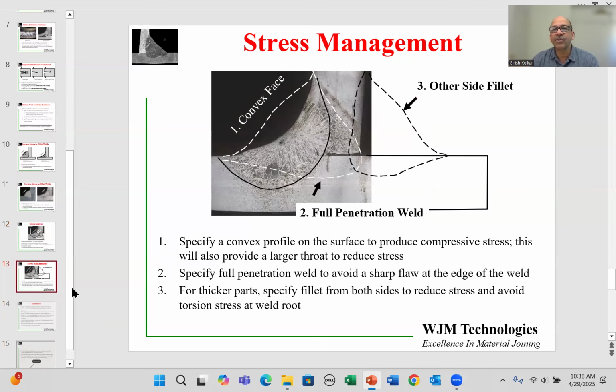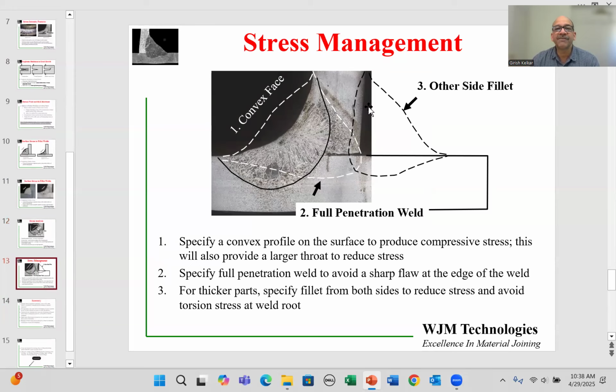So what can we do to manage the stress? The first thing you can do as a design engineer is to specify a convex profile on the face of the weld. And you can do that. As a design engineer, you can specify on the drawing that the weld should have a certain profile on the surface, and that requirement will supersede any requirement in the welding specification. The welding specifications oftentimes will allow slightly convex to slightly concave faces, of course, within limits.